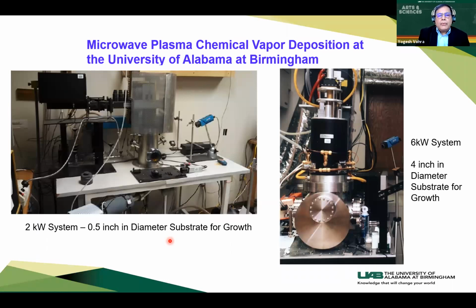So these are the 2 main experimental tools we'll be using when describing this research. Those are the microwave plasma chemical vapor deposition systems at UAB. Basically you use a microwave power source, which is 2.45 gigahertz, to excite your plasma. And then depending on the microwave power, you have the deposition area, which you can see by the size of this chamber here.